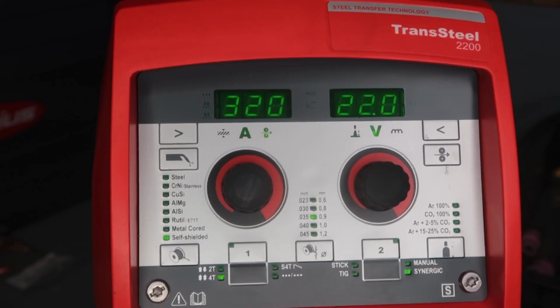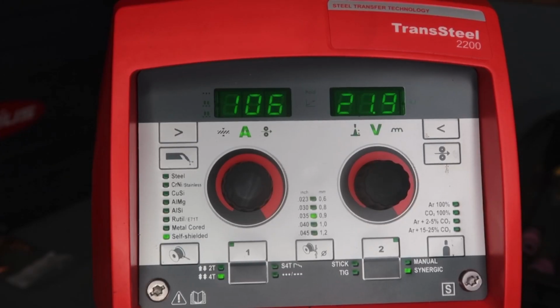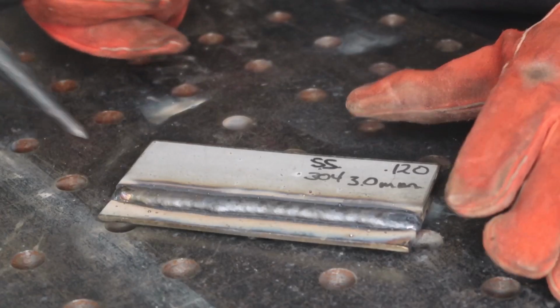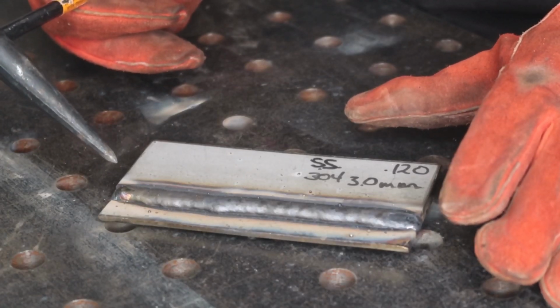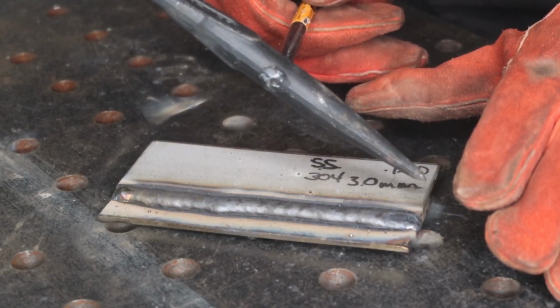We're running around a 5/8 contact tip to work distance, and you notice there's not a lot of spatter coming off this compared to conventional self-shielded wire. And we're running about 320 inches a minute at 21.5 volts, which is somewhere around 110 amps, depending on your contact tip to work distance. But I'm pretty impressed with this for self-shielded stainless. This is the first time I've welded with self-shielded stainless, and I can't wait to chip this thing.